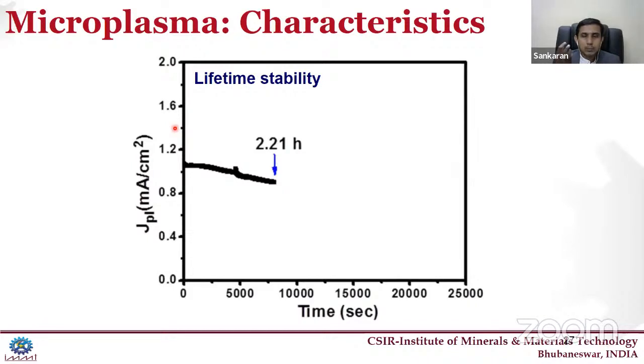So that material should withstand that electron emission, and even in that plasma environment it is very, very difficult. When you are supplying some other gases like hydrogen or maybe some oxygen, those are all etching gases. So it's very difficult to withstand the plasma for a longer time because the material will etch out completely. In that case, we need a highly robust cathode material. So when you are fabricating a microplasma device, the lifetime stability is an important parameter to be discussed.